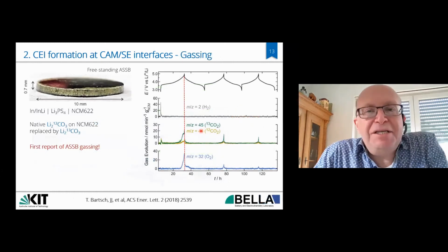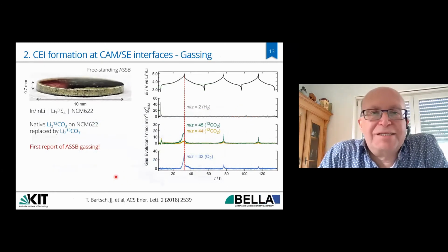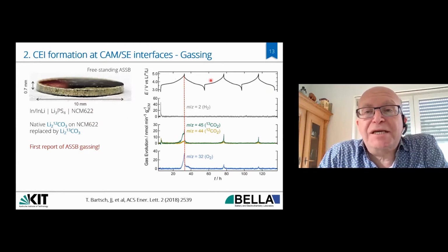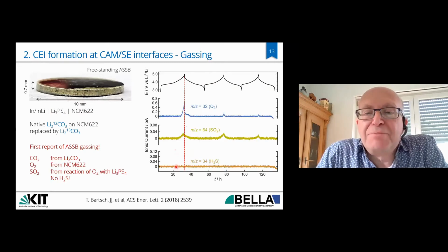Okay, now another indicator of the decomposition of the electrolyte is gassing. And what you see here is a pellet type solid state battery. There's a cathode on top. There's a relatively thick solid state separator, which is Li3PS4 in this case. And we use a battery with NCM622. And what you see here is the cycling of the cell, CO2 and O2 come out of the cell. So this is a DEMS measurement. Out of connected porosity of the solid state battery, gases come out. But what we see is there's also some SO2 coming out. So in fact, this is another indicator for the reaction between oxygen from the NCM material and the sulfide electrolyte, forming even gaseous side products.